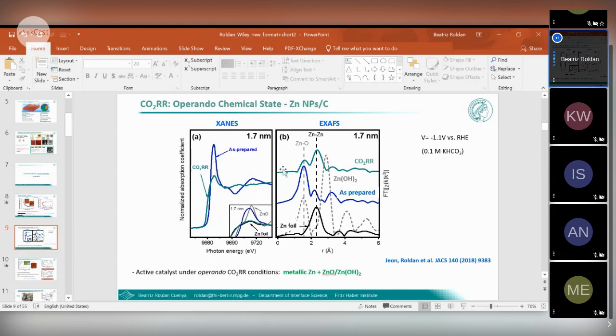But if you look carefully, and you look, for example, also at the extended X-ray absorption fine structure spectroscopy data, if you compare the as-prepared sample here, you see zinc-oxygen bonds, and under reaction conditions, even after a couple of hours at minus 1.1 volts with respect to RHE, you can still see the zinc-oxygen features, the zinc-oxygen bonds. And in fact, if you look at the structure with more detail, this looks more like a hydroxide. So what we learned from this study is that, first of all, small nanoparticles are not good if you want to make CO. They will favor the production of hydrogen. And on top of that, the catalyst is not metallic under reaction conditions. Even under this reducing potential, it's actually a hydroxide.